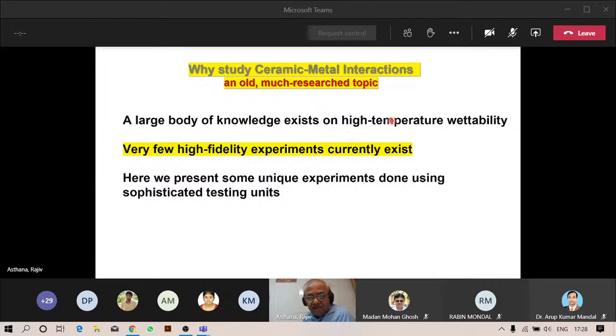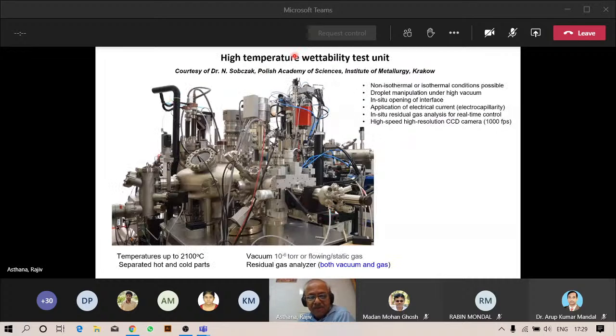So in the next slides in this lecture, I'm going to mainly focus on some unique experiments that I did with my Polish colleagues using some very advanced and interesting instrumentation that they built. So here is a high temperature wettability test unit that was designed and fabricated in Dr. Natalia Sobczak's lab. Earlier, she was at Foundry Research Institute, and then about a year and a half ago, she relocated as a professor and head to the Institute of Metallurgy and Materials in Krakow. This is the wettability test unit that can go to 2100 degrees Celsius, and you can do the testing for contact angle and surface tension properties, both under non-isothermal and isothermal conditions.